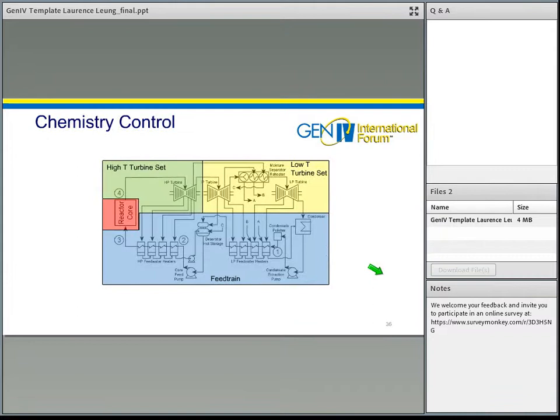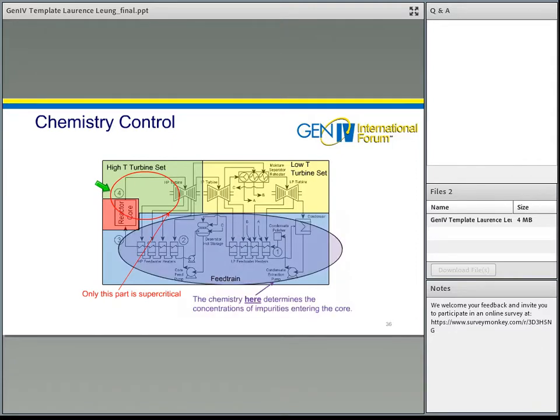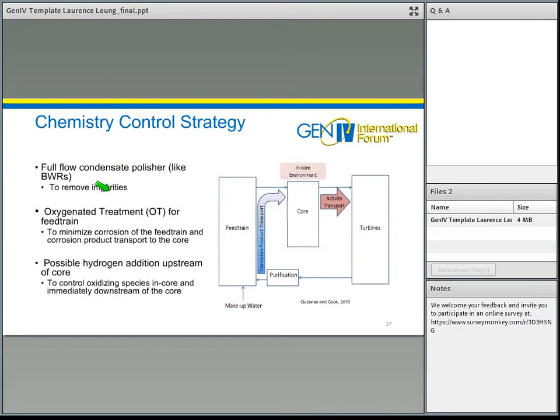I'll show you the same figure that we showed before in the materials section, but look at the chemistry control area. You can see that in the system, only this part is supercritical. The rest is just a low temperature and low pressure region. In the chemistry area, we determine the concentration of impurities entering the core, and thus we focus on the filtering. So what we propose is that you can use a full flow condensate polisher like in a BWR to remove any impurity from the fuel cladding.